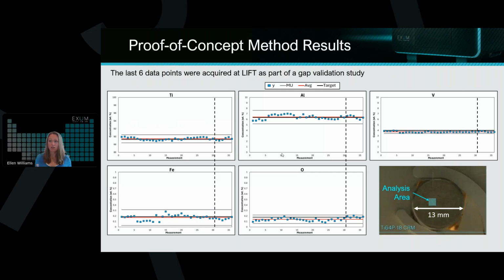The other thing that I want to point out is that the last six data points that we acquired here were what we did at LIFT as part of a gap validation study, where essentially we developed the method in our own facility in Denver, Colorado. We then brought the method steps to the LIFT Massbox and said, let's do the same method here, verify that we get the same results, and you can see that we did for all elements. All of those elements landed within that measurement uncertainty range, giving us the confidence that this method can be applied to multiple Massboxes and can be repeated by multiple users.